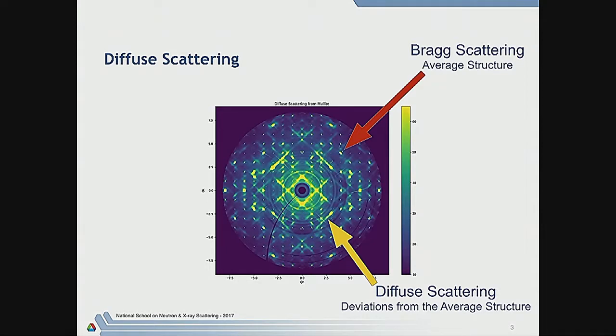I think I should have put this equation in my talk, but we're measuring S(Q). S(Q), if you integrate over all frequencies, gives you a T equals zero snapshot of the structure. So if the atoms are all vibrating, you freeze them at some position and you get the average of all those snapshots.